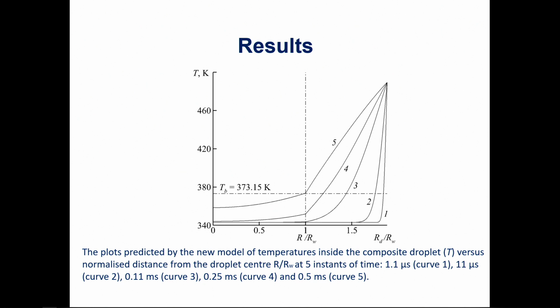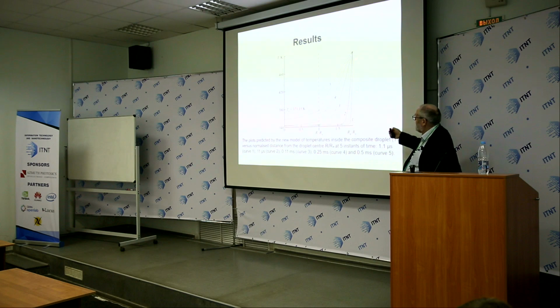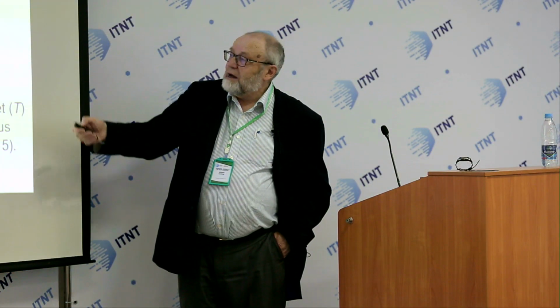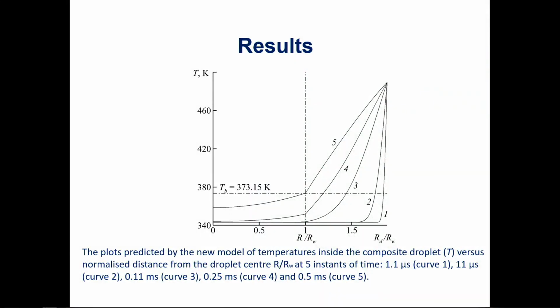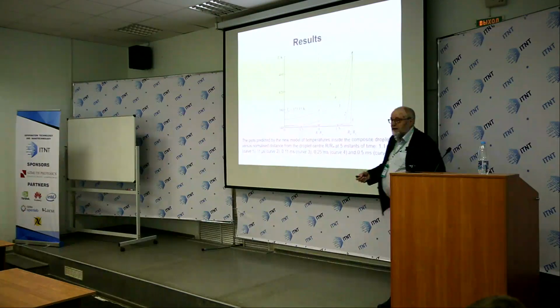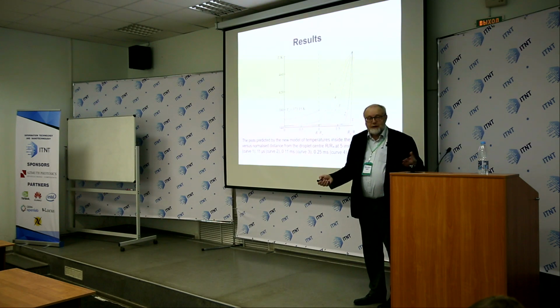So, for example, initially we had a jump in temperature between the droplet and the ambient air, and then we have a gradual spread of heat inside the droplet. And this leads to the gradual increase of temperature at the interface between the water and the fuel. And eventually, at some stage, that is time instant 5, this temperature at the interface between water and fuel reaches the water boiling point. And we assume that at this stage we have microexplosion. Strictly speaking, it will be puffing, which leads to microexplosions.